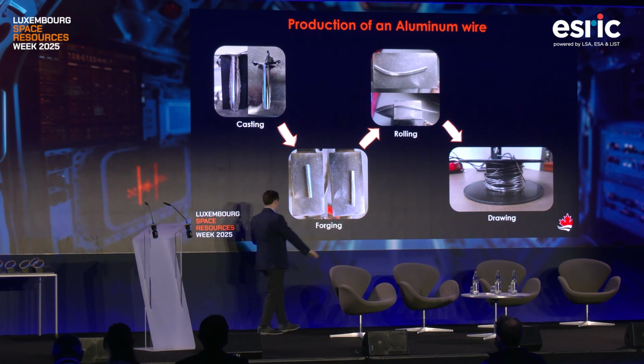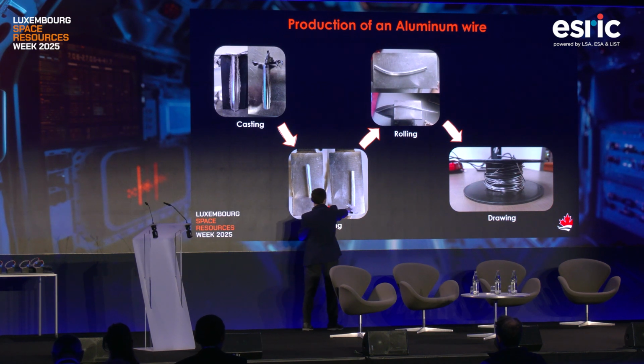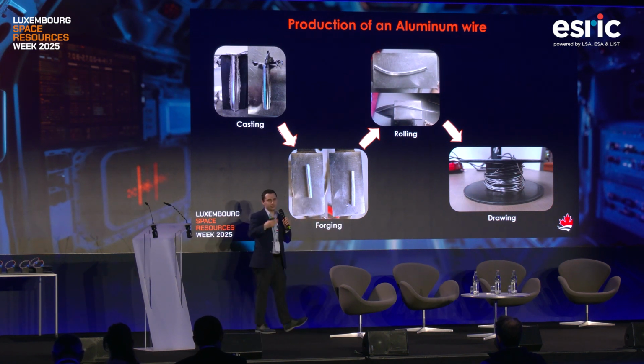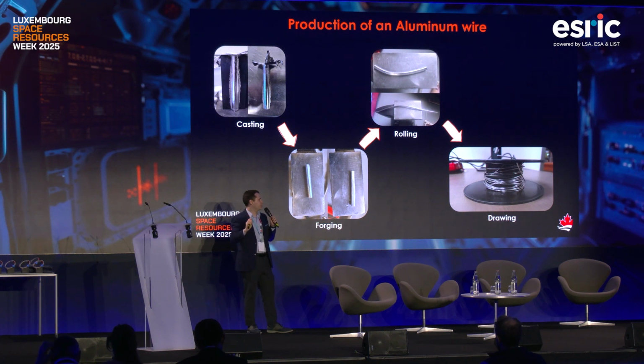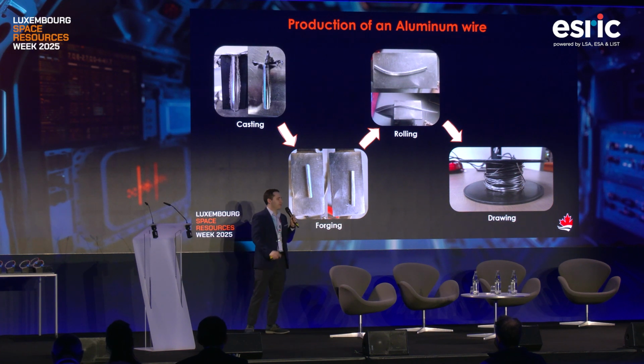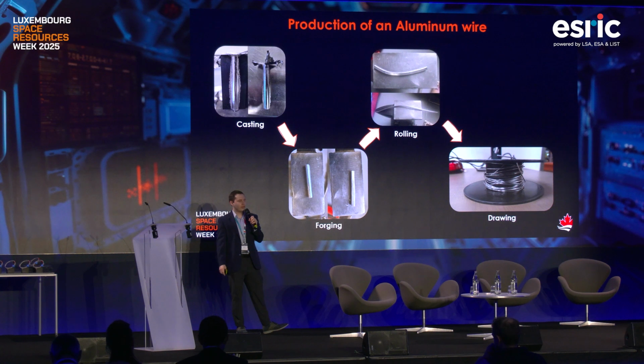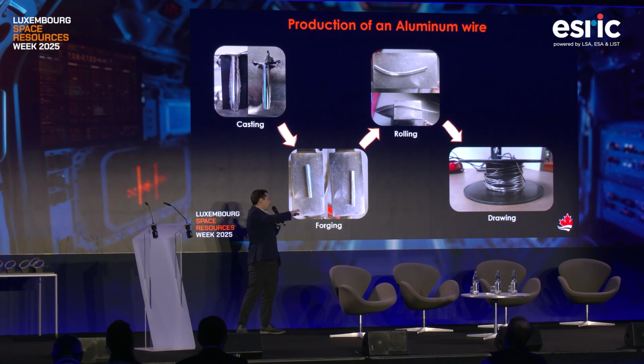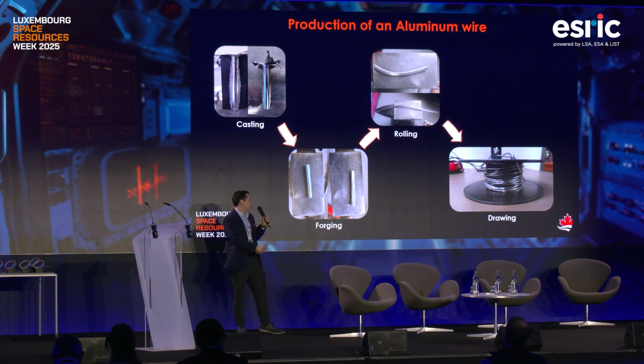Basically, we have our cylinder, and then this has a squared cross-section because it's easier for it to go through rolling. So then we did the rolling part. That's mainly to make it longer, reduce the size of the cross-section, so that we could do wire drawing afterwards, because it requires a very small cross-section. And the last part was to do wire drawing with the aluminum. And as you can see in the last picture, that's a spool with the aluminum in the spool.